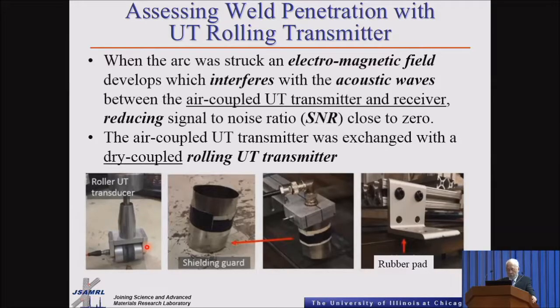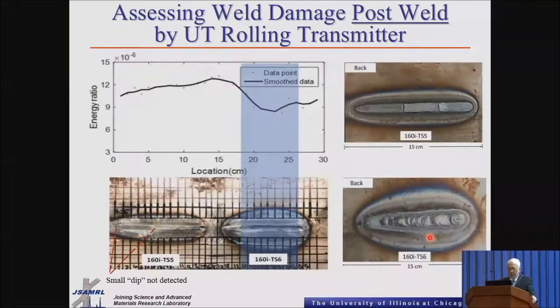As a matter of fact, I showed the figure before, in which you can see that the rolling transmitter was always behind the torch. We put some shielding on one of the sensors, the sensor for the receiver, and put some rubber pads to electrically isolate the scanner. And these are the results using the rolling transmitter. Again, this is done post-weld. Remember, this follows the deposition of the weld, so this was post-weld.